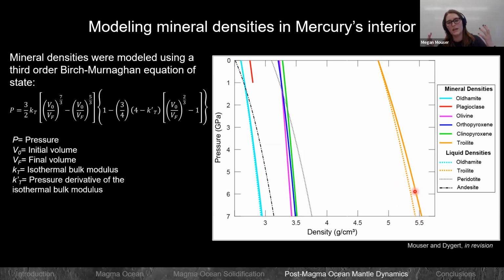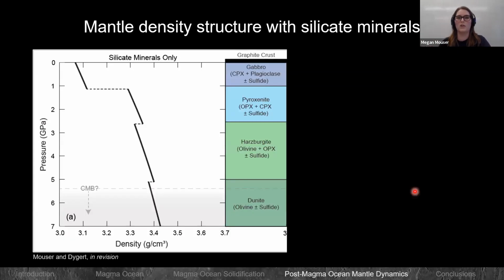So if we take these modeled densities and predict what this would look like in terms of a density structure in Mercury's interior, this is what it would look like for the scenario with just silicate minerals. We're not introducing sulfides yet. And I have kind of this gray region down here because of the core-mantle boundary, or the pressure depth of Mercury's mantle. There have been some suggestions that it's maybe 5.3, 5.5, maybe up to 6, and in some of the older papers I've seen closer to 9.